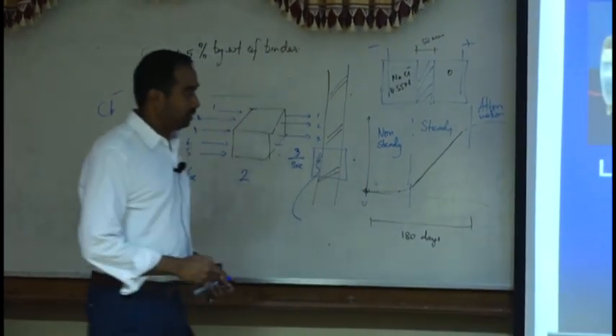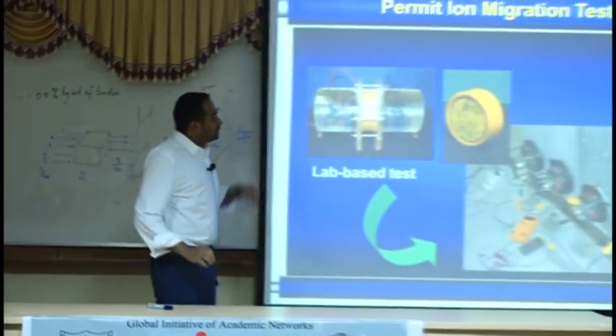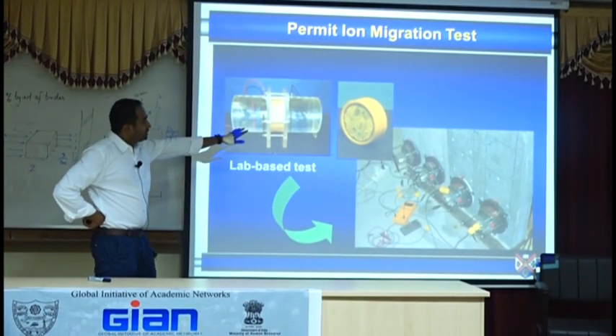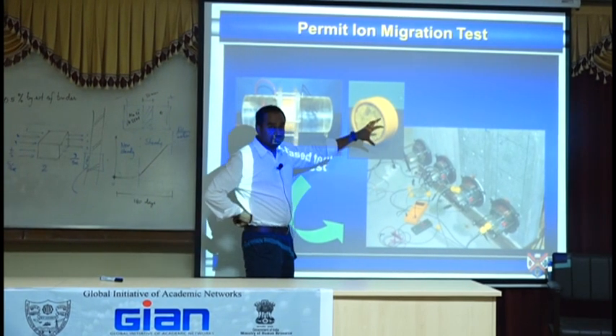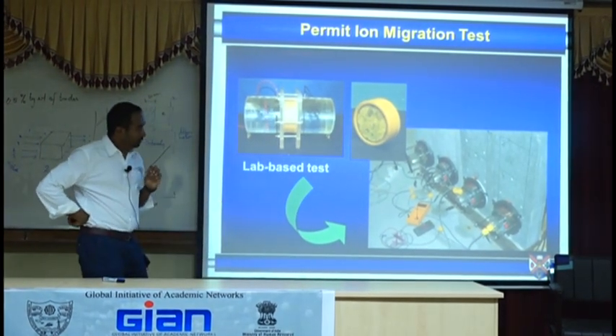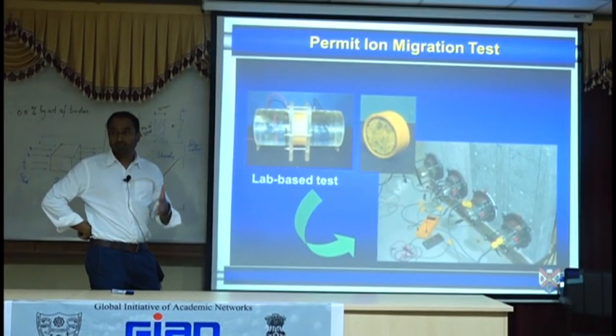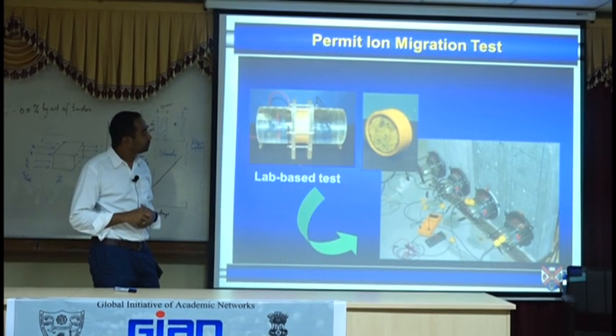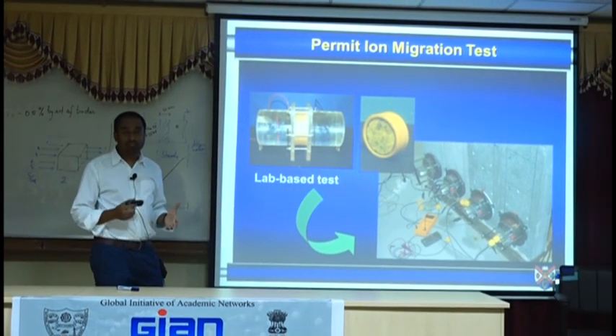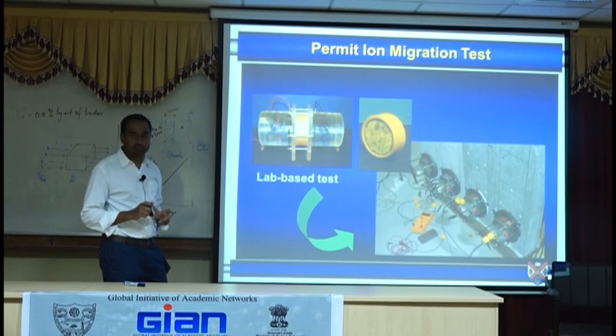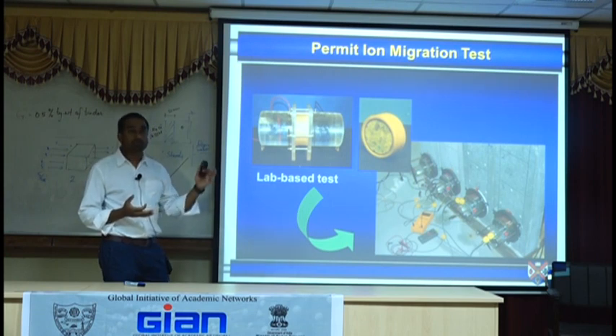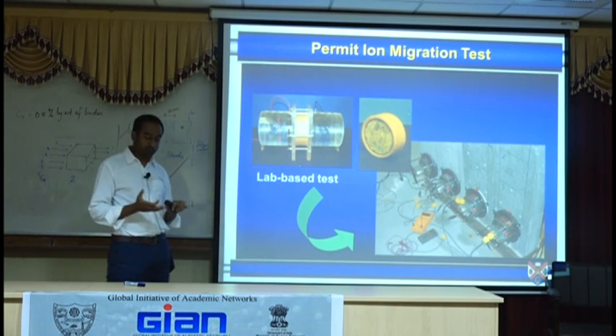So, where did we go? Our challenge was to go from a laboratory-based test where you need a core sitting in the middle of it, to the surface. We were always looking at surface-based tests. We didn't want to take a core. There are different reasons for that in the UK. First of all, taking cores is not feasible for certain kinds of structures. Taking cores requires you to send somebody to take the core and bring it back. It is costly in the UK, it's costly in Europe.